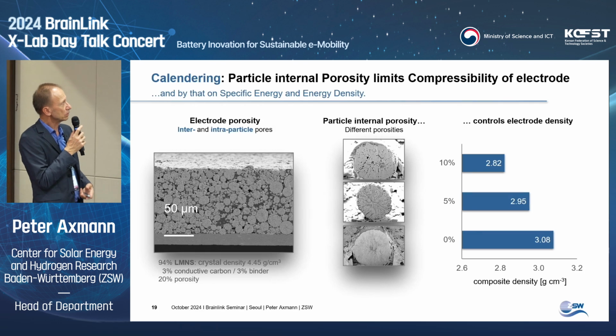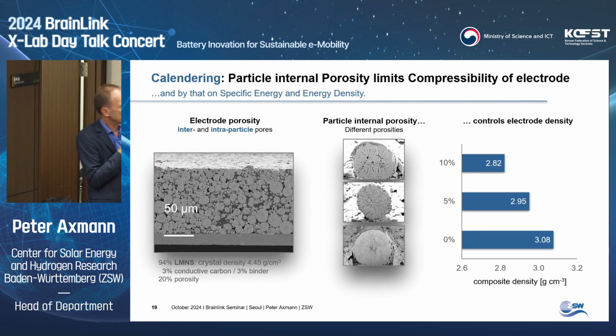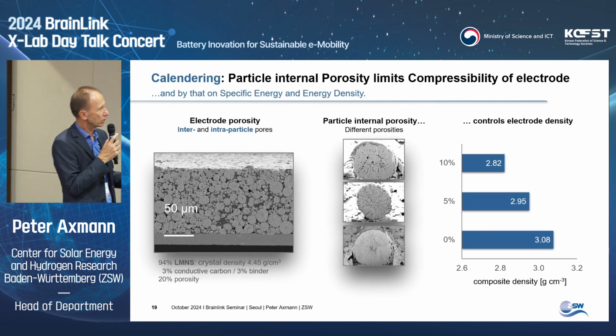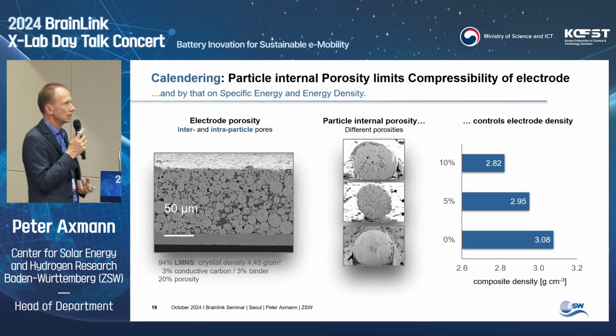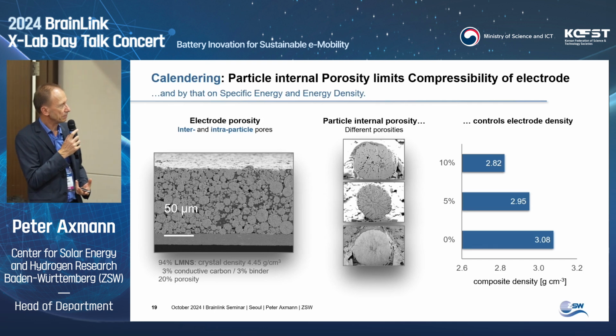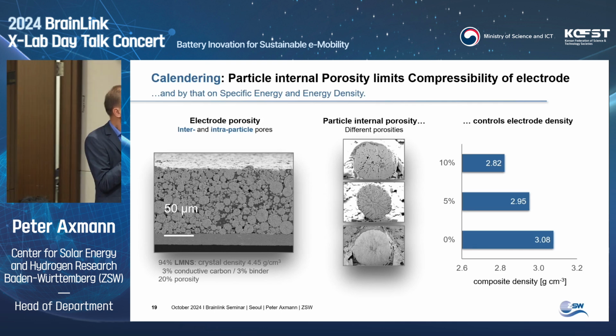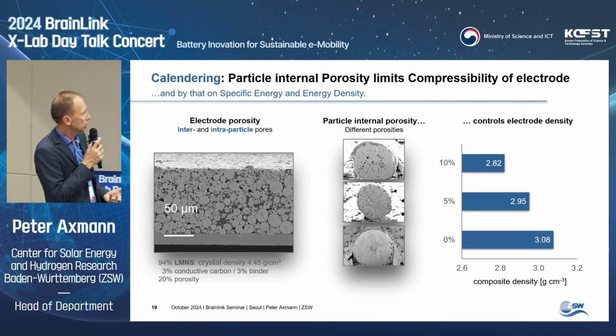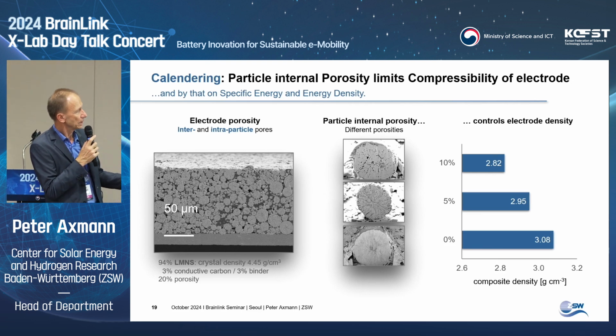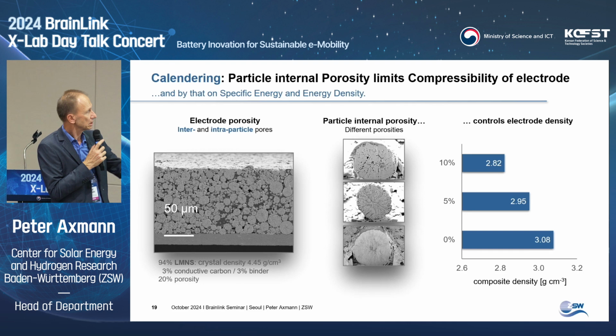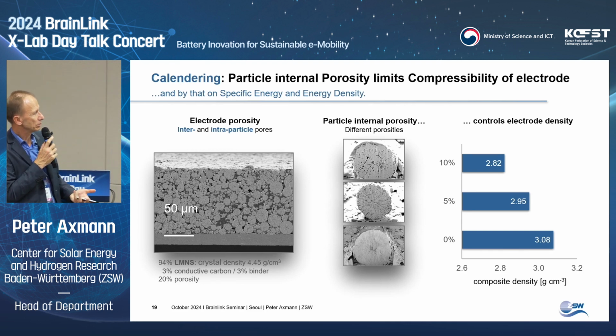On the other hand, if you go to densification, you densify the electrode and press out the porosity between the particles to get more materials into a cell. So you can compress only the porosity which is between the particles. But there's as well an internal particle porosity. So this is what I showed for the tap density of the material.